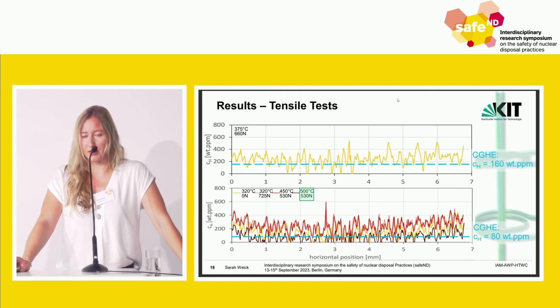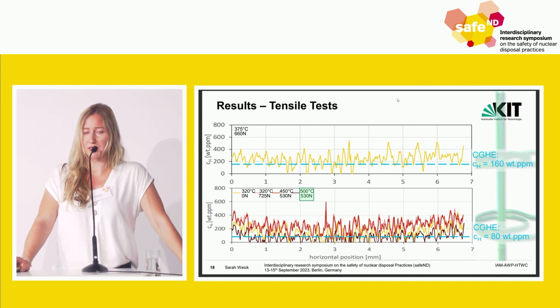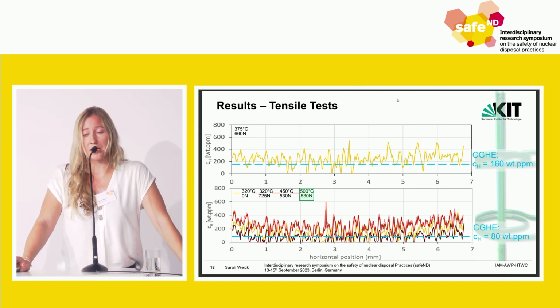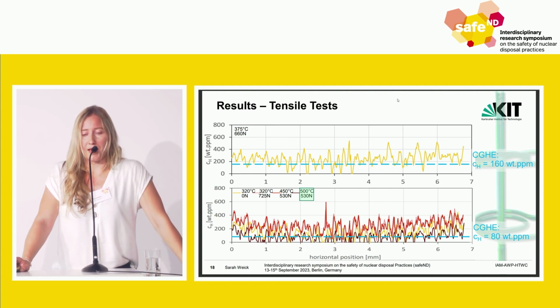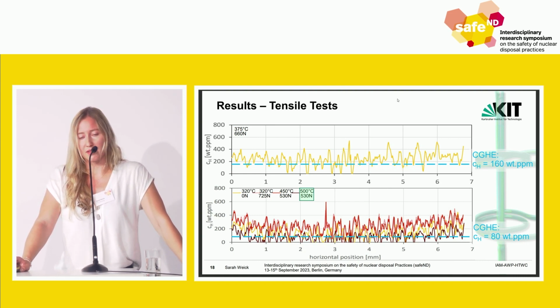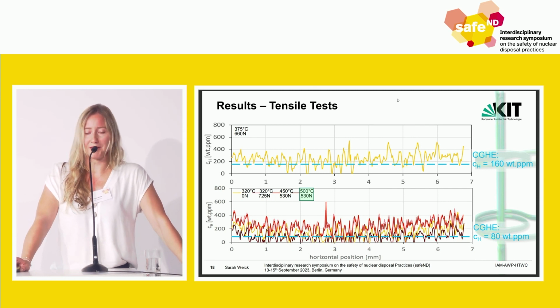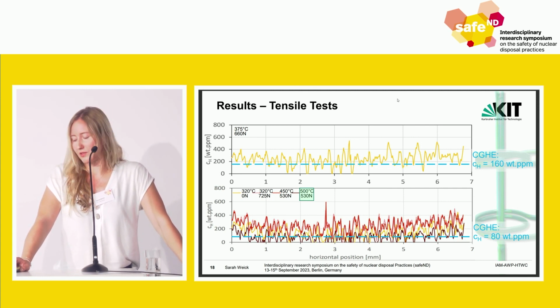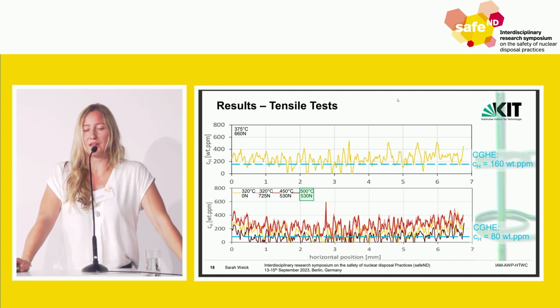But nonetheless, you see clearly the difference on the lower image: when we have a plastic range, which would be 500 degrees and 530 newtons, we see the hydrogen moves. In this case, it was outgassing. But before that, in the elastic range, we couldn't see any changes, also due to the very slow timescales we had, about a maximum of 1 day, which led us to the expectation that maybe it's just a local dissolution and precipitation process that happens during the elastic stress application.